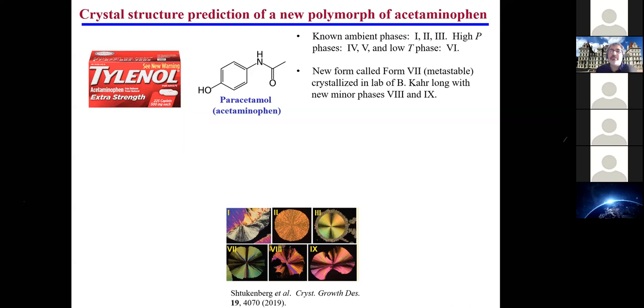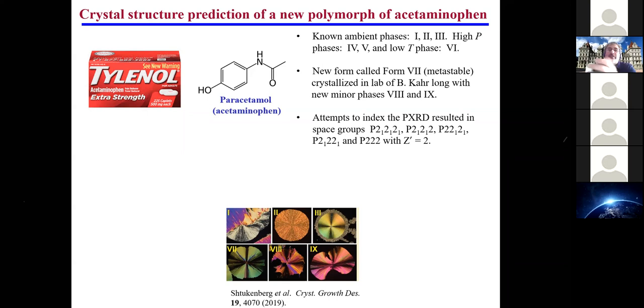And it turns out one of the polymorphs that they got, a very stable one, which is called phase 6, I think, or phase 7, they wanted us to do some CSP on this, all right? And so they got their powder X-ray diffraction patterns, and they tried to index them themselves, and all of the things that came up when they tried to do this are in this P21 type of space group category, right? But when they evaluated the energy using DFT, density functional theory, they all came out with really high energies. They said, okay, you guys give it a try.